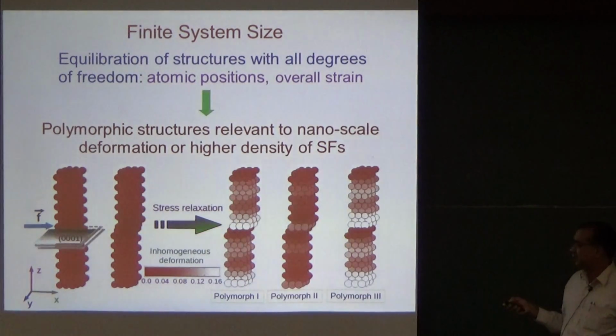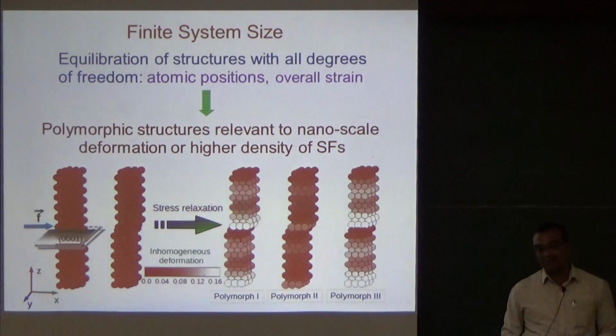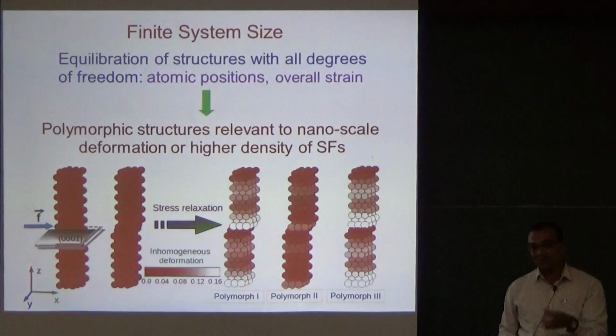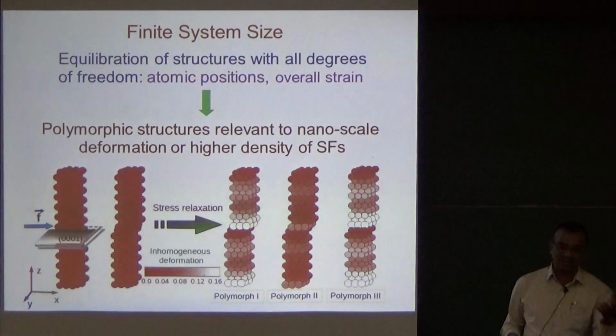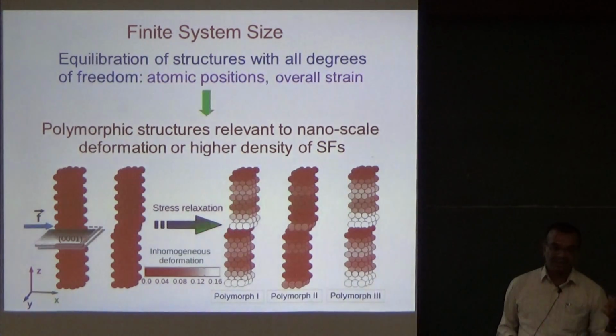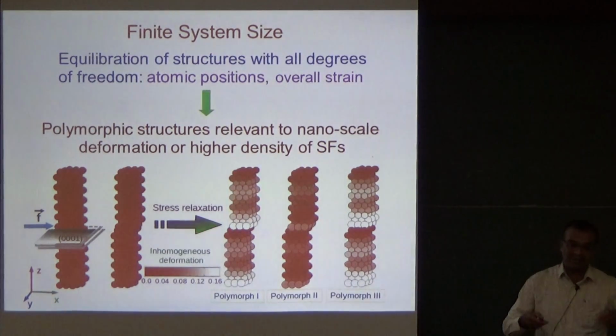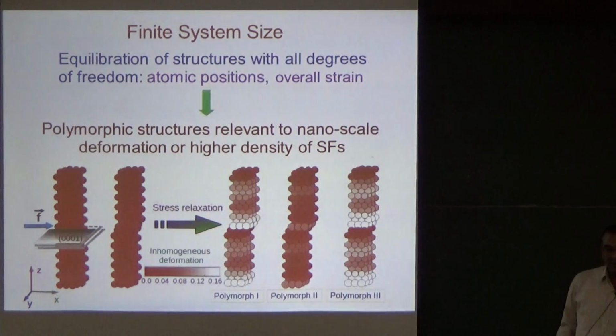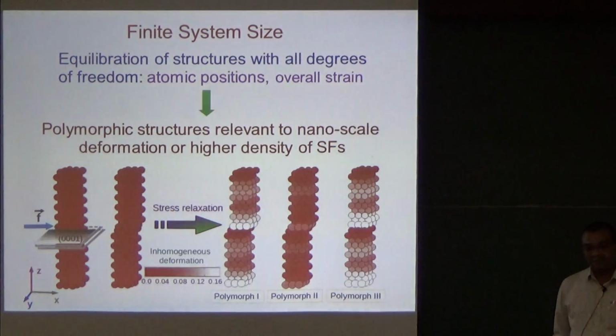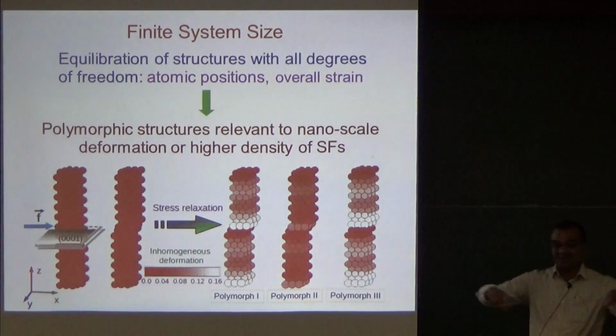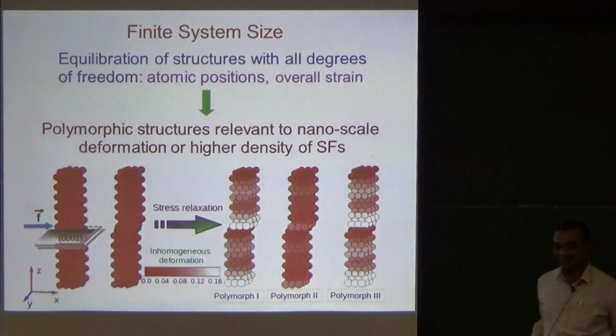Yes, experiments were done on a nano rod of titanium, and there they could see this very similar thing, although they interpreted it in a different way. So there were no grain boundaries in it. It's a nano rod of titanium, micron size, submicron. But the measurement is done on one single rod, which is a continuous chunk.